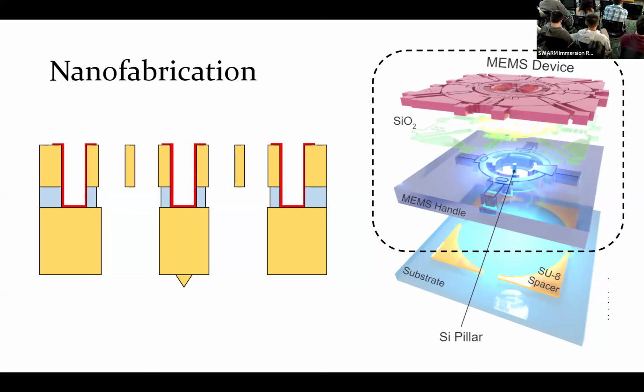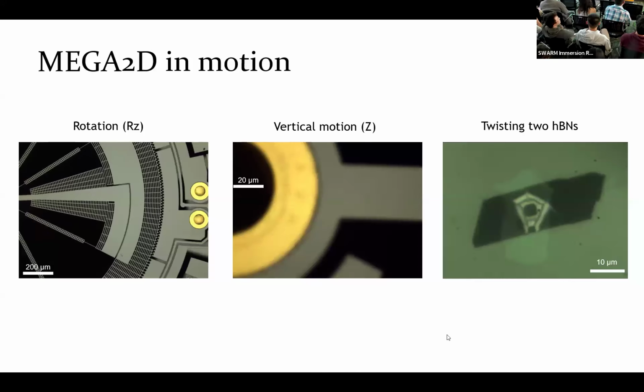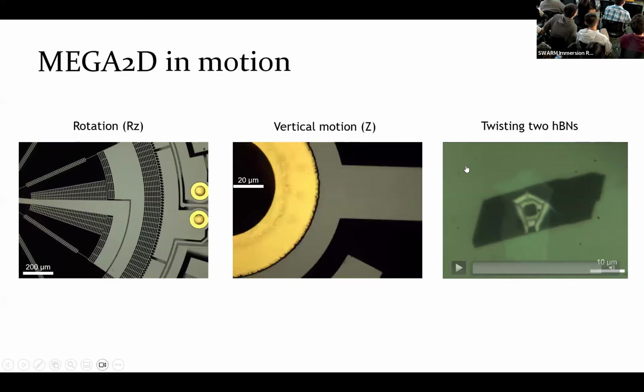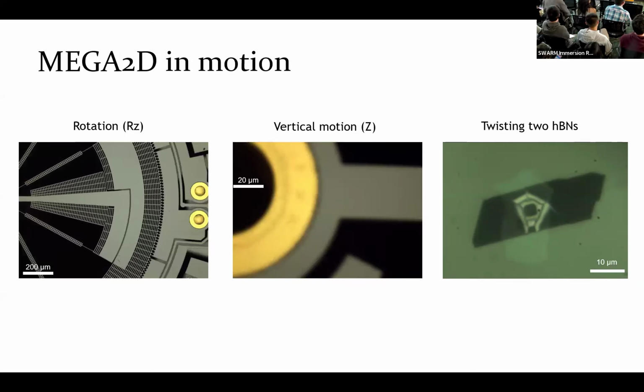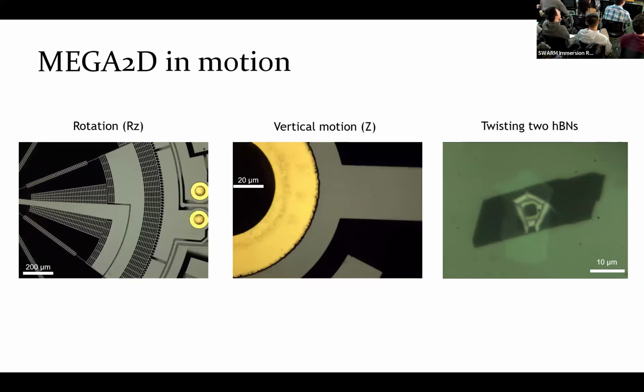The chip also has to be flat from the start, and that's guaranteed by the quality of the wafer, which is flat within, I guess, a few nanometers on this size. The other thing, as someone already asked, is that the SU8 spacer has to be flat. If these are flat enough, then the flatness between the 2D material and the substrate is guaranteed. We can actually measure that flatness by doing some interferometry between the pyramid and the substrate. If you look through the microscope, the color changes as you change the distance between the MEMS and the substrate. From that color, you can estimate how much tilt you have. This is from interference of light.